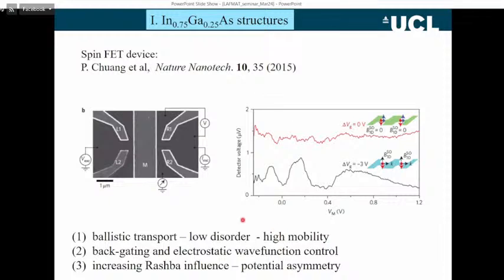This device relies on ballistic transport, so we have to have low disorder, high mobilities. We also have to be able to understand how the gates operate in these systems, how we can control the wave function with an applied gate voltage. We also have to understand how this spin-orbit coupling effect occurs, how this Rashba effect occurs, how the confining potential asymmetry relates to the spin-orbit coupling. So that's the basic device that we're trying to measure.